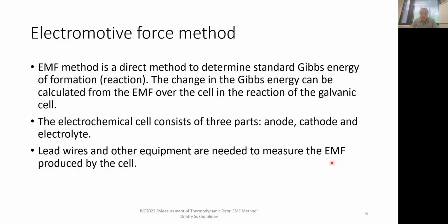And since we're talking about high temperature, pyrometallurgical applications, our electrolyte is solid. If we want to study oxide phases, then a solid oxide electrolyte with oxygen ion conductivity is very favorable. In addition to these three main parts, the galvanic cell is equipped with lead wires and also with high input impedance electrometers to measure the EMF generated by the cell, and with modern ways of doing it, some other appliances. Let's talk later about that.